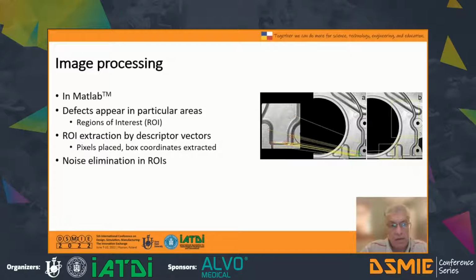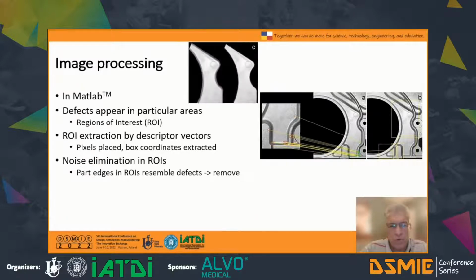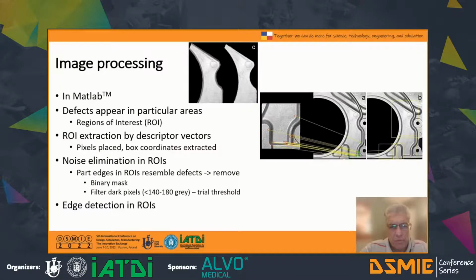Then in the regions of interest, in the images of ROIs, we had to do some noise elimination because the edges of the part that belong to regions of interest may resemble defects, so we had to remove them. You can see in this picture at the left hand side the edges that appear, somehow blurring the profile, and to the right hand side you can see the same thing after removal of these edges. So in order to do that, we applied suitably defined binary masks, then we filtered dark pixels. The threshold for filtering was defined by trial and error.